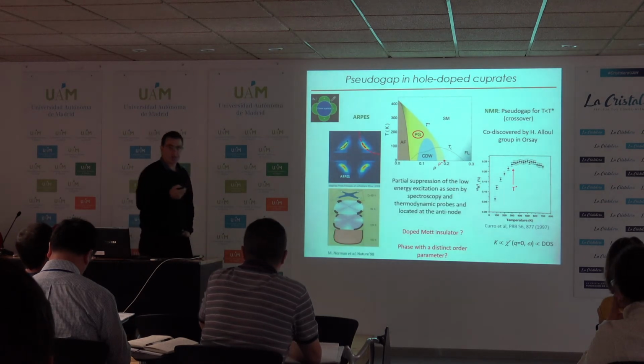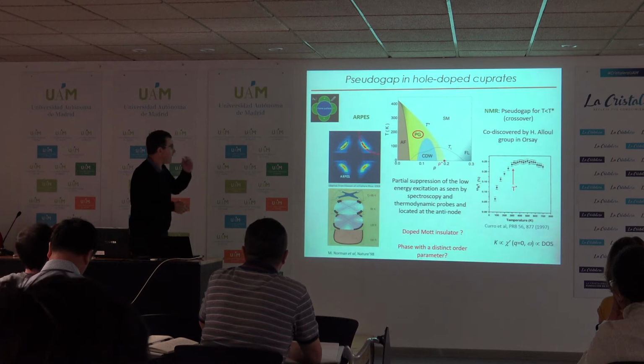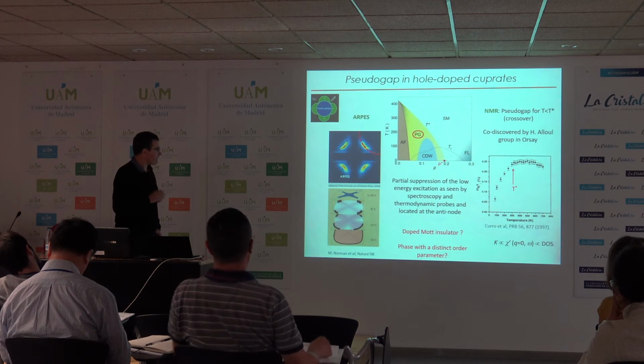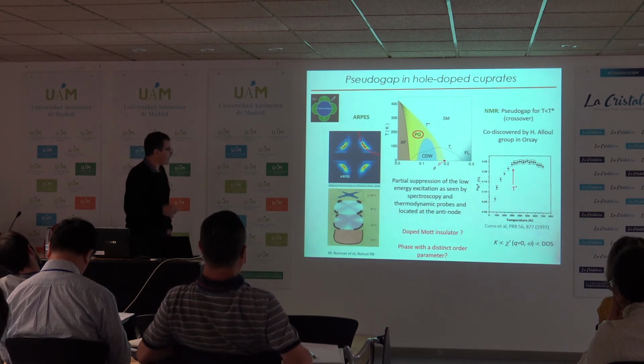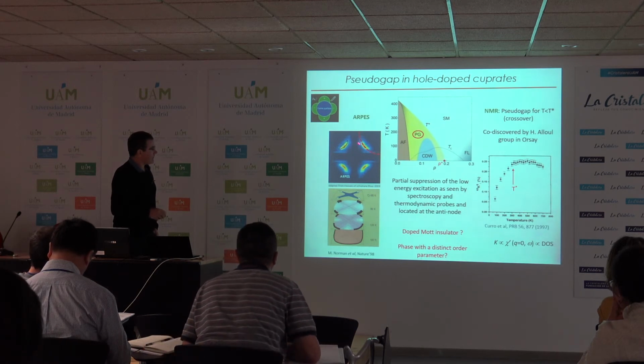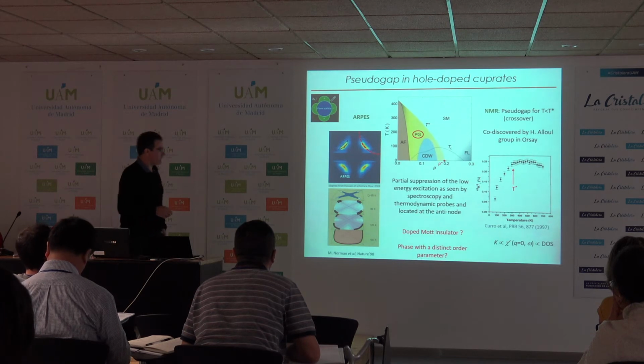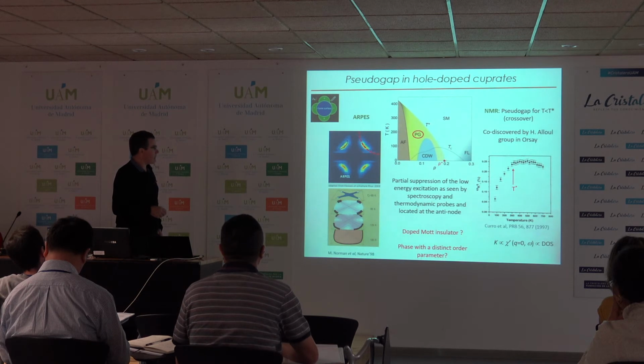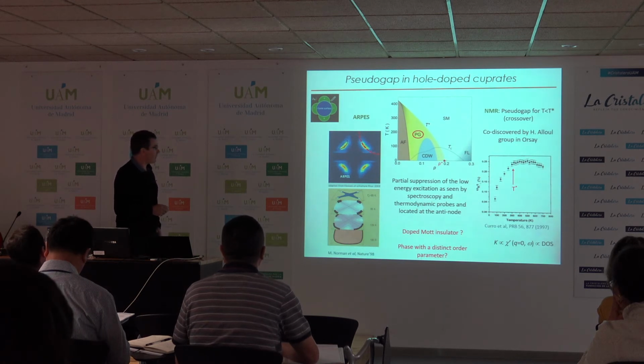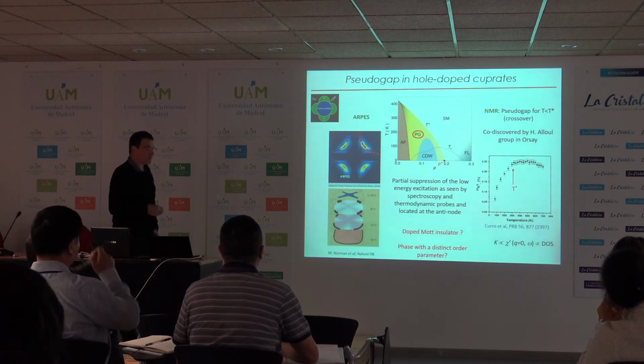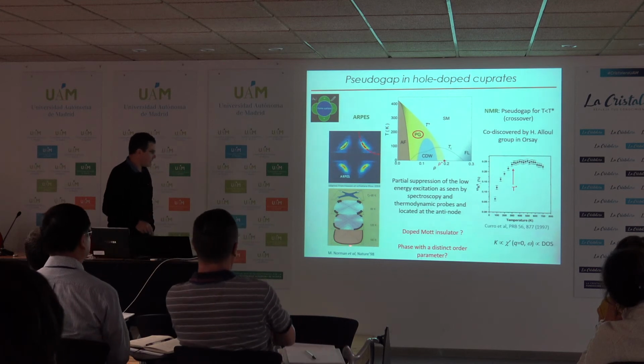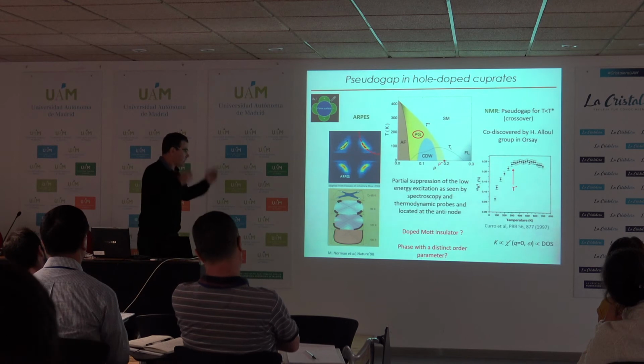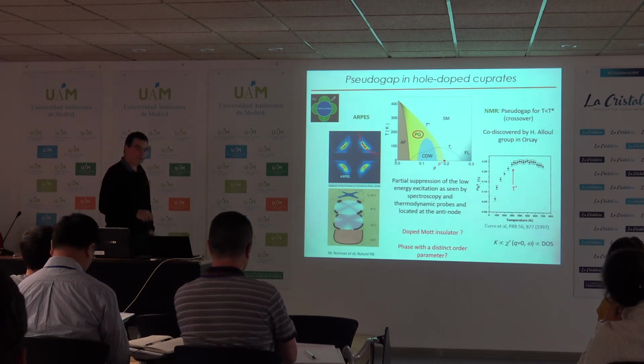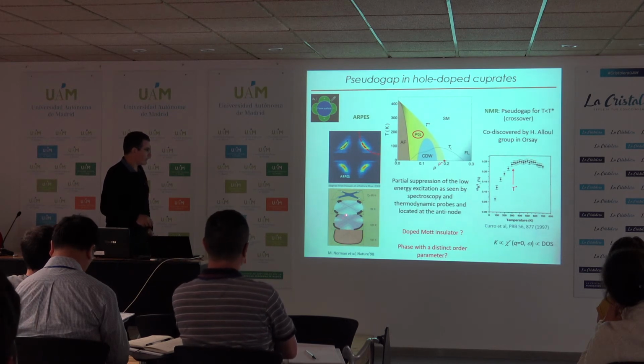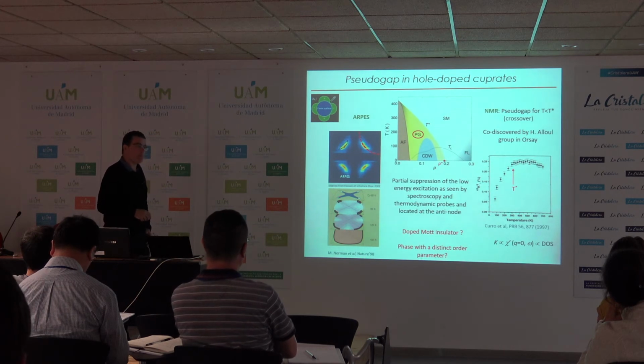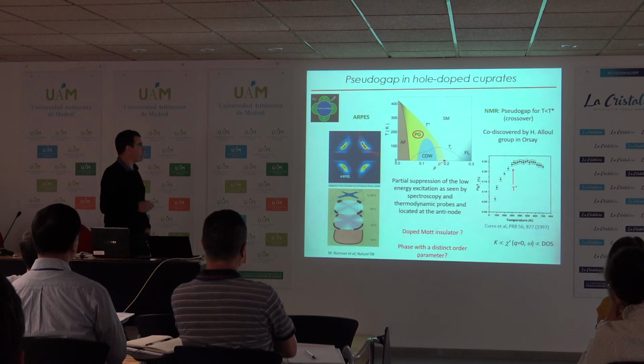A spectroscopic definition of the pseudogap, from ARPES measurements, is a partial suppression of the low energy excitations. Here I show you ARPES measurements, where the band structure calculation Fermi surface is in red. This is a large hole cylinder, and what they see is that when you enter the pseudogap phase, the states at the antinode disappear. Basically, there is a collapse of the Fermi surface at T star, and this cartoon shows what is believed to happen versus temperature. You have the large hole-like cylinder at high temperature, and when you cross T star, the states at the antinode disappear, leaving Fermi arcs, which become points in the superconducting state, with the d-wave signature.